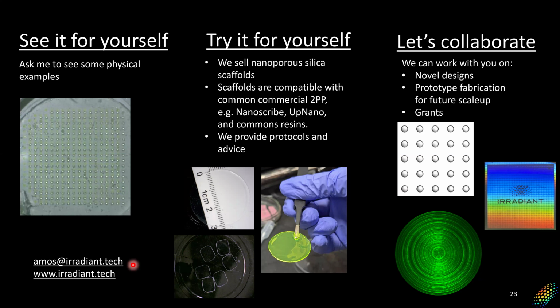Okay. And the associated question in depth, so the patterning in Z: is it one layer pattern, then cure the polymer, then you rinse the rest and do it again? No, you don't need to rinse. We have liquid resin and you go through and polymerize the full structure, and then you wash out after doing everything. If it's buried and you fully polymerize it, there's not much to wash out. You have to be careful if you're making a full shell, like a sphere that's strongly polymerized so it forms a boundary, with nothing polymerized on the inside. That can get tricky. We haven't found applications that need structures like that. If you do, there are ways to deal with that depending on the constraints of the application.